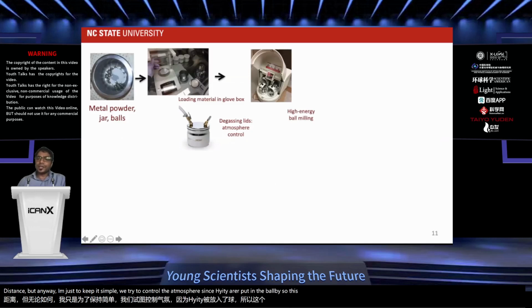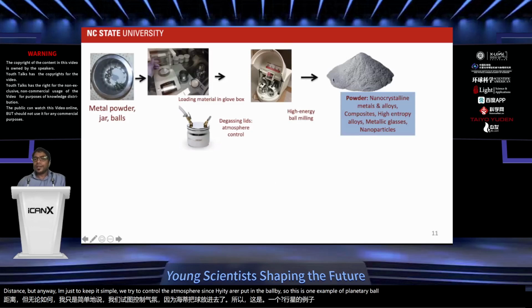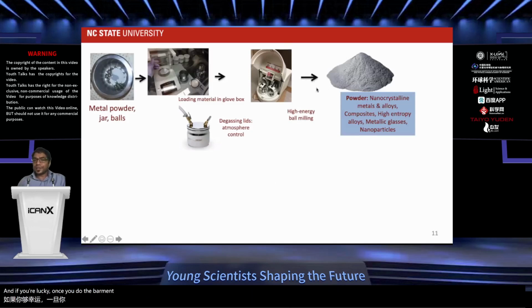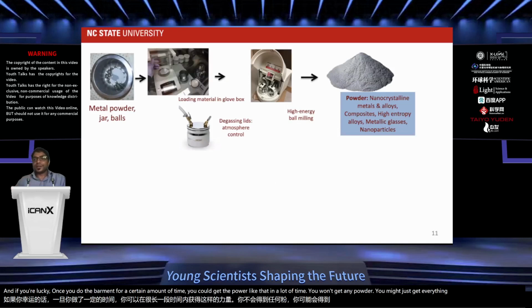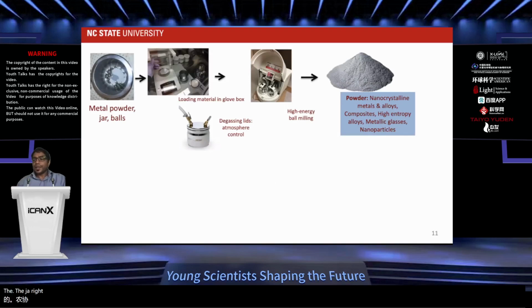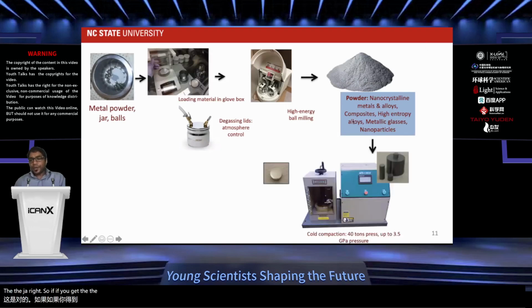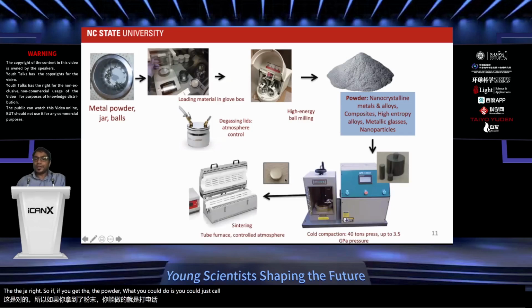This is one example of a planetary ball mill. If you are lucky, once you do the ball mill for a certain amount of time, you could get the powder like that. And a lot of the time you won't get any powder. You might just get everything stuck to the ball bearings and the jars, right? If you get that powder, you could cold compact it, then sinter it to make the components or the test coupons.